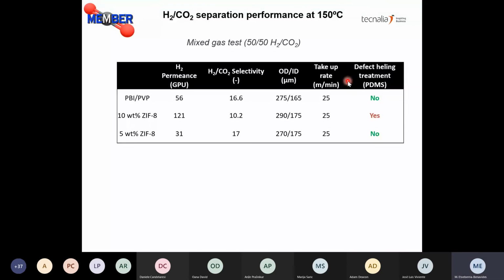As in the previous project for the pure PBI membranes, the PDMS defect healing was not required. So this is quite a good achievement. Then we prepared some mixed matrix membranes at 10% ZIF-8 loading. We managed to increase the hydrogen permeance, but selectivity was quite below the selectivity of the pure PBI, and in that case, a PDMS defect healing treatment was required to heal the defects.